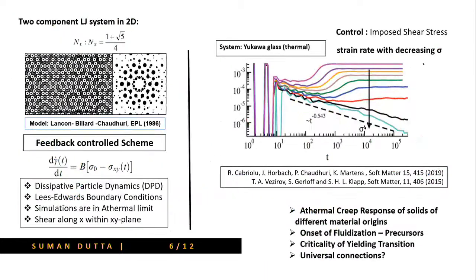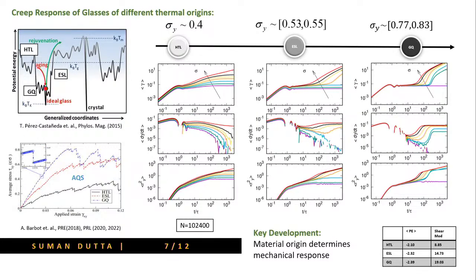So exactly a similar kind of thing we try to address: whether that is achievable in creep or not, and whether we understand this change in the dynamical response under creep within this kind of framework or not. So we take these different levels of glasses. We have HTL, ESL and GQ. HTL is the high temperature liquid, the glass prepared from high temperature liquid states. ESL is the equilibrated supercooled liquid, the glass corresponding to the equilibrated supercooled liquid, and GQ is a gradually quenched sample. So this is a very low energy state, this is a mid energy state, and this is the high energy state, and we are looking at the creep response of these different glasses.